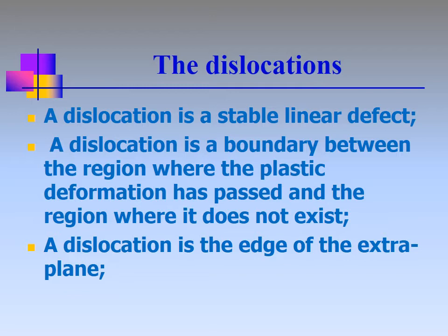As noted above, plastic deformation in a crystal does not occur instantaneously but gradually, along certain atomic planes in certain directions. In other words, in the process of plastic deformation, at any instant of time it is possible to detect a moving boundary between regions in which plastic deformation has already occurred and an area where there is no deformation yet. This boundary is the line of dislocation.